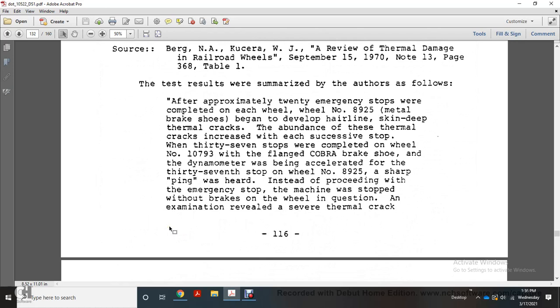The test results were summarized as follows. After approximately 20 emergency stops were completed, each wheel, with the number 8925 metal brake shoes, developed hairline, skin-deep thermal cracks. The abundance of these thermal cracks increased with each successive stop, through the thirty-seventh stop completed on wheel number 10793 with a flange Cobra brake shoe.